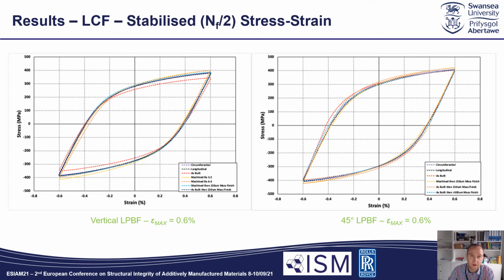So then looking at the same plots now under the stabilized or half-life condition, and as expected, the as-built specimens display the lowest stabilized stress range across the 2 orientations, plus the greatest level of plasticity when looking at the width of the loops, which means it is experiencing the largest level of permanent deformation upon the application of each fatigue cycle.